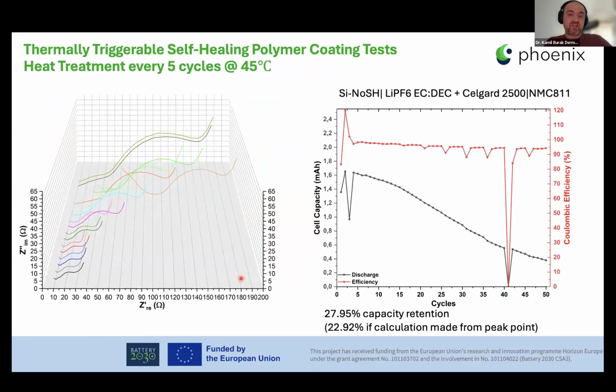Of course, these tests have been done at a continuous temperature, like 25 degrees at room temperature or 45 degrees in the climate chamber, for the whole duration of the testing time. But we were also curious about testing in this interrupted way. So every 5 cycles, we tested the cells at room temperature, and every 5 cycles we heated them up to 45 degrees, and then cooled them down, and then continued the testing to see if there is an effect on self-healability in terms of the